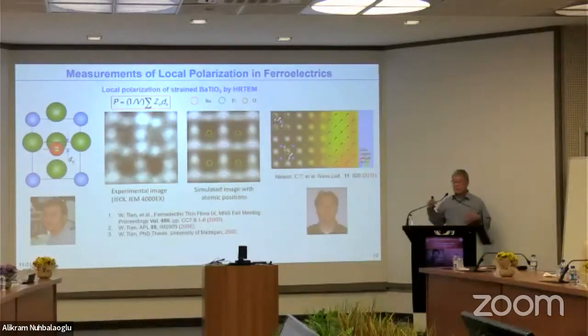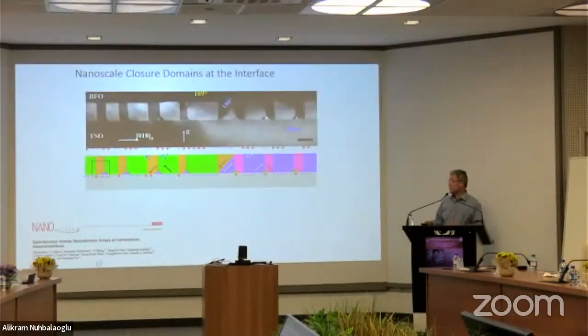The TEM used was the very powerful TEAM microscope located at a national lab, a US Department of Energy program. So we had a very stable high resolution microscope at that time, using the technique developed by WK. And Chris was able to develop a tool to automatically map the atomic displacement from unit cell to unit cell, so that you can use this method to discover unknown phenomena.